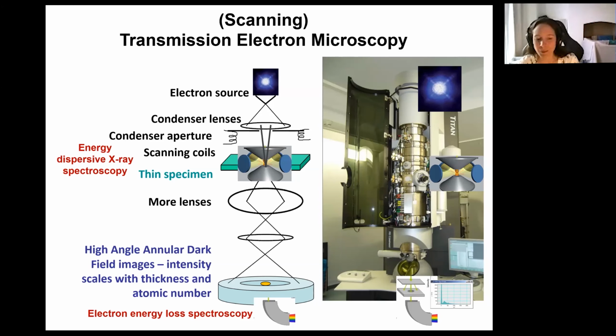From the intensity that we get in the annular dark field image, for a monolayer specimen like hexagonal boron nitride, you can tell which are the boron and which are the nitrogen atoms. Of course, we can combine all of these imaging modes with compositional information. In that annular dark field mode, we can use those bright field electrons going through an electron energy loss spectrometer. These will give us information about the energy that the electrons have lost, and therefore information about bonding, about oxidation state, about plasmonic resonances.